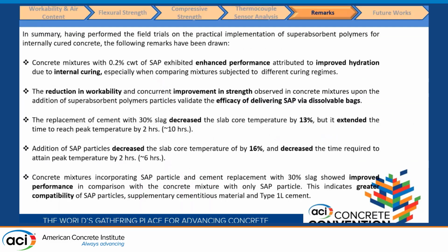Now, in summary, some of the key takeaways we were able to extract from our research. We found that the concrete mixtures using SAP exhibited enhanced performance. This can be attributed to improved hydration due to internal curing, especially when we compare these mixtures subjected to different curing regimes. Also, the reduction in workability and improvement in compressive strength in the concrete mixtures with added superabsorbent polymers validate the efficacy of delivering SAP using dissolvable bags.